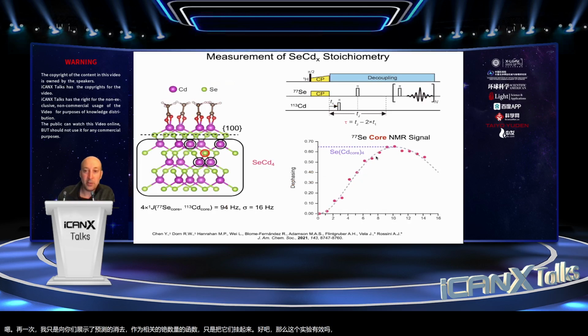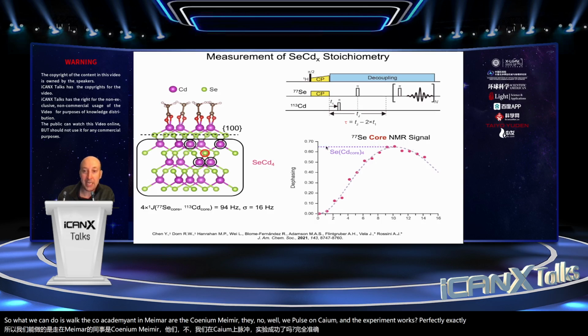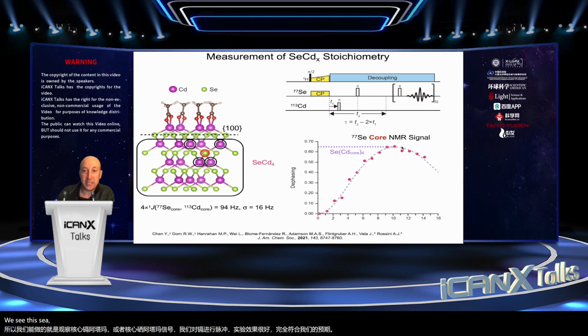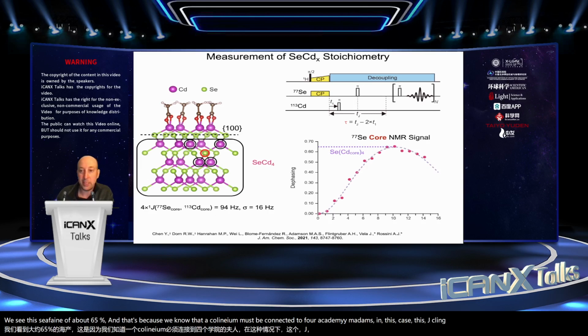What we can do is watch the core selenium NMR signal while we pulse on cadmium. And the experiment works perfectly, exactly as we would expect. We see this dephasing of about 65%. And that's because we know that a core selenium must be connected to 4 cadmium atoms. In this case, this J coupling is around 100 hertz.